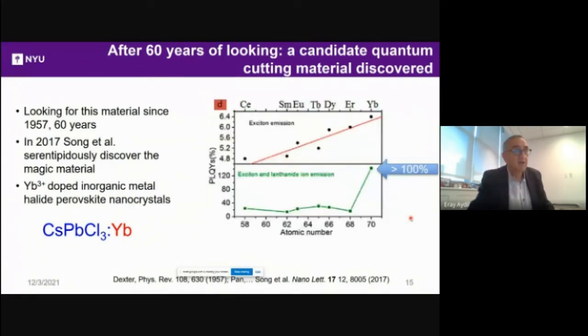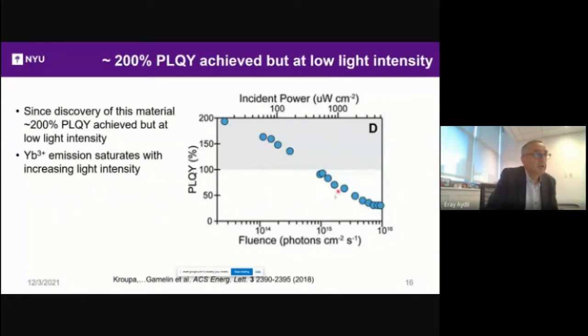And what they discovered was that when they looked at the photoluminescence quantum yield, that is how many infrared photons you're making per UV or ultraviolet photon, for most of the rare earths, it was about 30%, what you would expect. But for ytterbium, they got over 100%, which is a clear sign of quantum cutting, that you're getting on average more than one photon in the near infrared per photon in the UV. Okay. Now, since the discovery of this material, people have reached 200% photoluminescence quantum yield with this material, shown here.